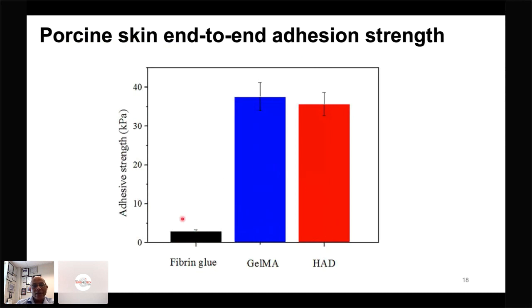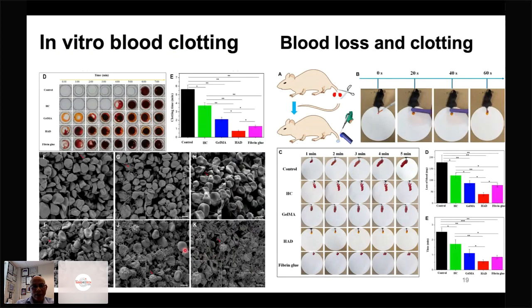So you can see that the adhesive strength of this new gel was as good as Gelma, which has been reported to have, as I said, excellent adhesion properties, but it was much, much higher than fibrin glue. So we were excited about that. And then we continued to look at the blood clotting assays. And again, a lot of data. I apologize, this slide is crowded, but the message is very simple.